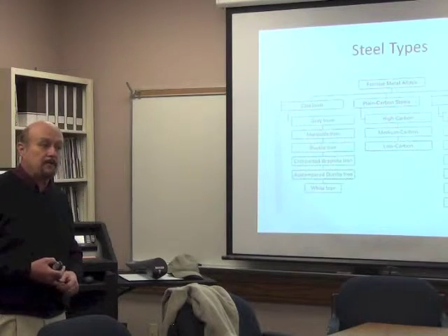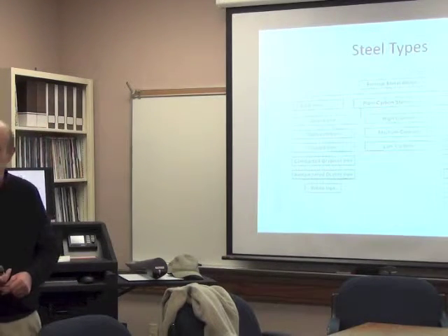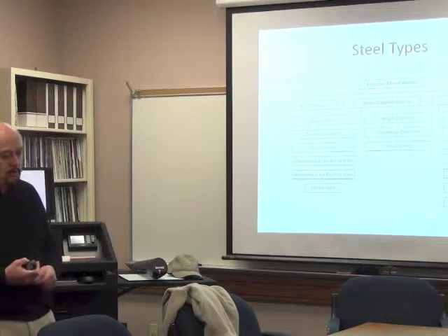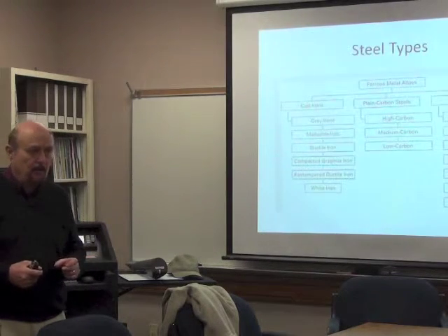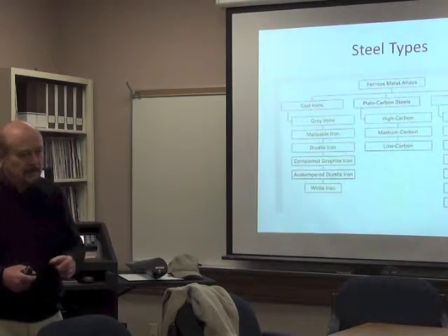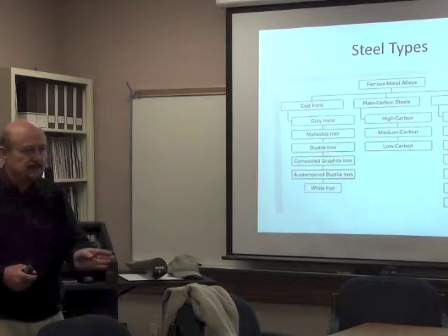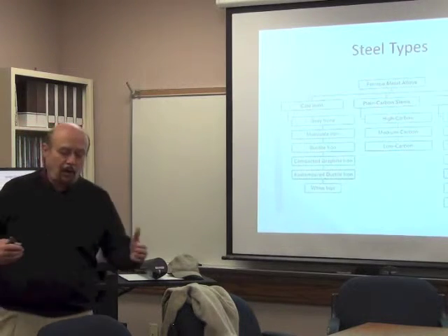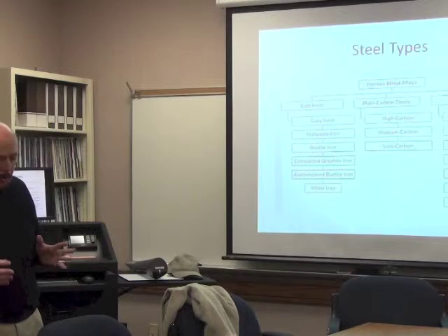Okay, well, there are spectrometers that they can use, but they're very expensive, right? So last year's project is where Tyler Dalkey used a grinder, and you hold a specimen of metal at constant force against this grinding wheel, and a specific size, and it creates sparks, okay? And it creates a spark pattern, and by looking at the spark pattern, you can distinguish between different types of steels. That's really what he discovered. He looked at about 10 different types of steels, okay?